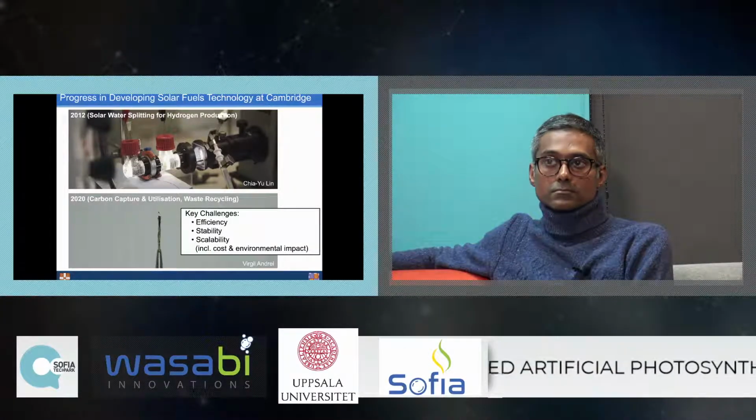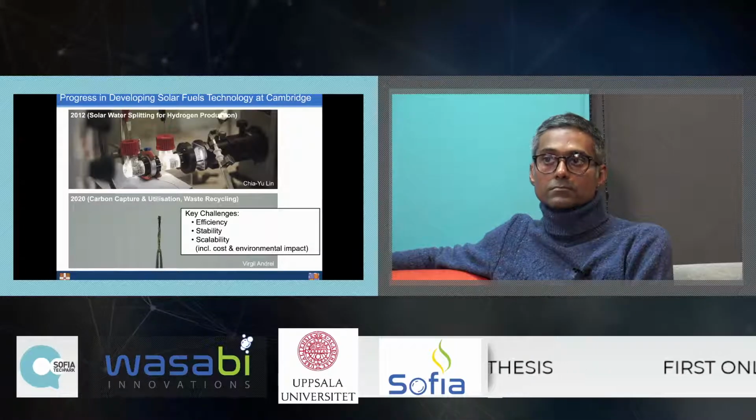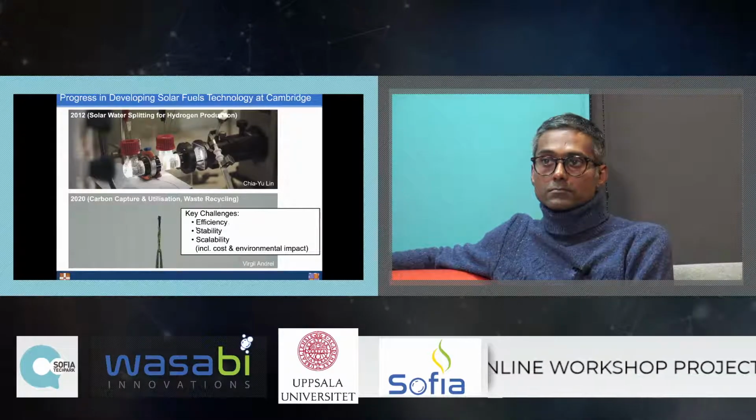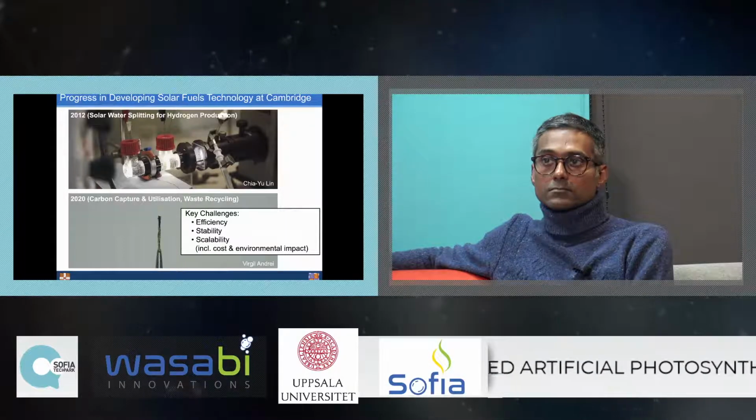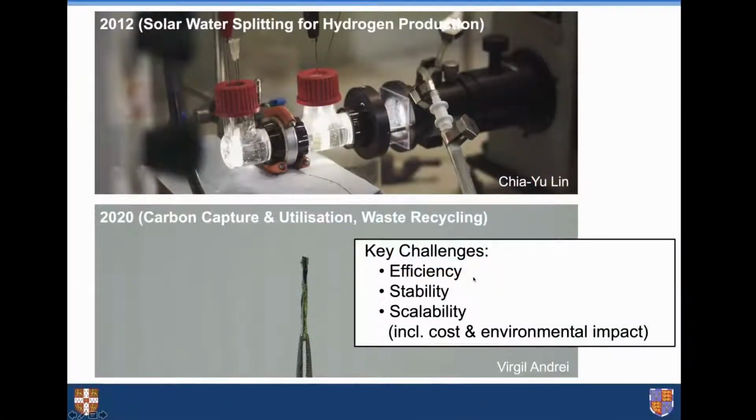Which challenges stay ahead? This is not just challenges for us, but for the community in the broadest sense. Efficiency: very often, a rough number of 10% will be needed for commercialization. Our systems are quite significantly below this value at the moment. Stability will be required to operate for years. In our case, usually we test them up to a week. Some of our panels or systems can operate for longer than a week, but we will not run them much longer than a couple of weeks at present, which is not enough.